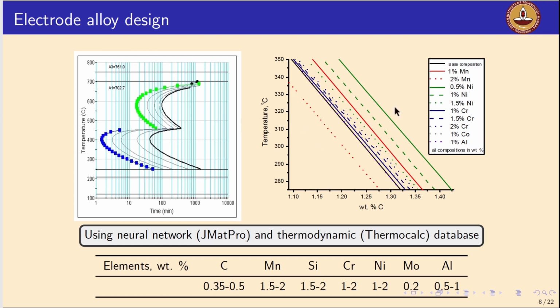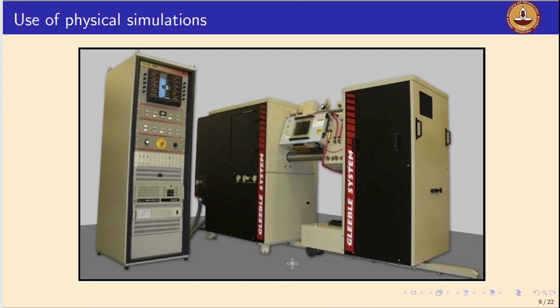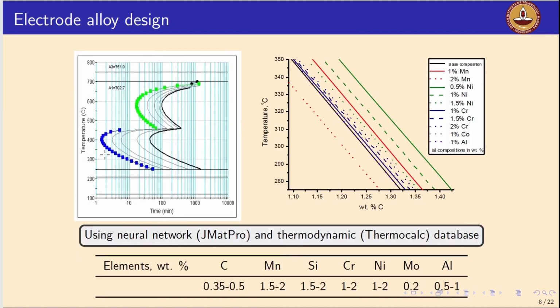And apart from the CCT diagrams, we also predict what is known as the paraequilibrium phase boundaries, and that is to ensure the maximum carbon partitioning when the austenite is held at isothermal bainitic holding temperatures. So we identify the candidate chemistry. Once we identify the candidate chemistry, what we do is we design the electrodes based on this candidate chemistry with variation in the alloying elements, which can give us some freedom to play around with respect to weldability. Right. So first we identify the candidate chemistry, and then we make the electrodes with a plus or minus 0.3% of carbon, and the other alloying elements suitably varied.